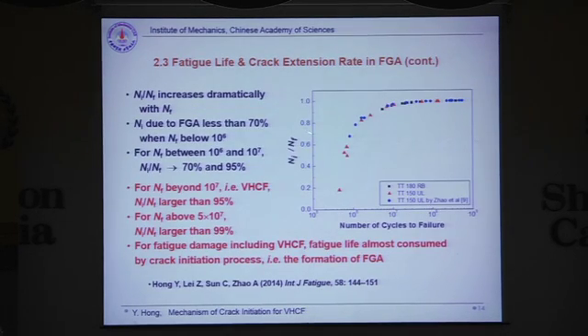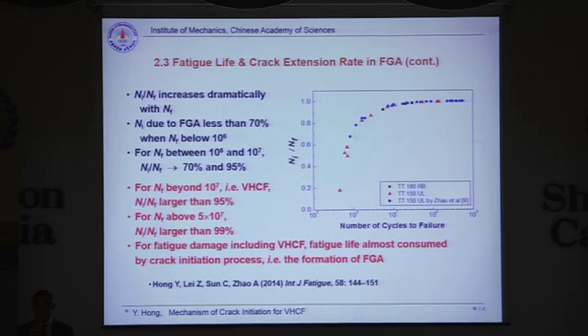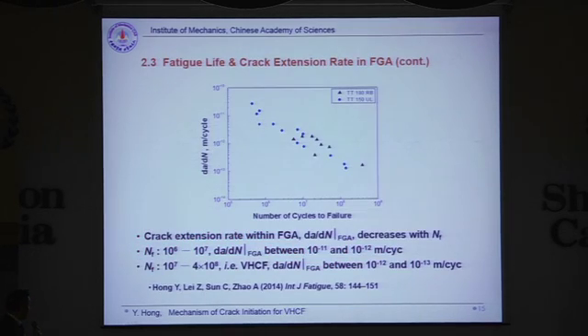Therefore, we get this result showing the normalized fatigue life due to initiation as a function of the number of cycles to failure. The important thing is that in the regime of very high cycle fatigue, the normalized fatigue life is larger than 95%. It means that for this kind of fatigue failure, the majority of fatigue life is consumed by crack initiation. We also estimate the crack extension rate within this small range of crack initiation. The value is 10 to the minus 12 to 10 to the minus 13 meter per cycle.